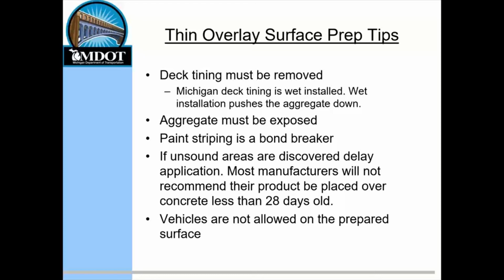Like Greg said, paint striping is a bond breaker. Paint striping has to be removed. And if any unsound areas are discovered, you have to delay the application. Most manufacturers will not recommend their product be placed over concrete less than 28 days old. And lastly, once the surface is prepared and ready for the overlay, vehicles are no longer allowed on the prepared surface, except for the one vehicle that is distributing the epoxy and the aggregate.